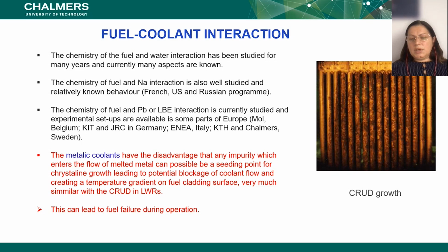So what can we say about that? Well, the metallic coolants do have some clear disadvantages. Any impurity which enters the flow of the melted material can possibly be a seeding point for crystalline growth. So basically you are growing crystals on the surface, and we know that can block channels, and then if the channels are blocked, the coolant flow is not working properly. That means that we have areas where the temperature is going to be very high, and then we have the swelling, and then we have the potential holes they will produce, as you have seen earlier.